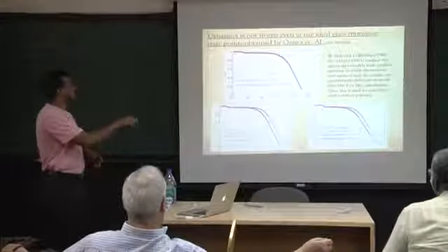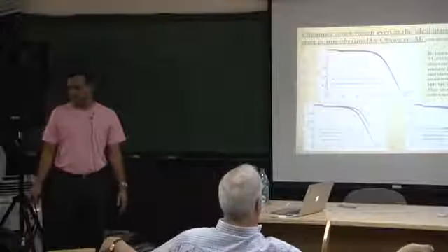So you just pick up 4-5 state points where, according to this calculation, entropy has to be 0, so your time scale has to be infinity, and we did MD simulations. You see that, for a couple of these state points, the corresponding time scales are not infinity; they are of the order of 10 to the 6 or 7 at max. So these are systems where, even in simulation, you can equilibrate the system. Forget about experimental time scales. Experimental time scale will be 10 to the 14.